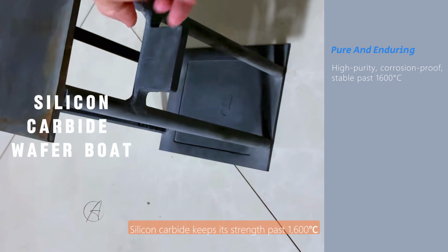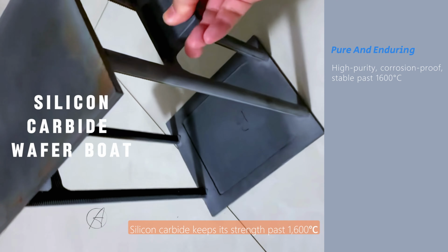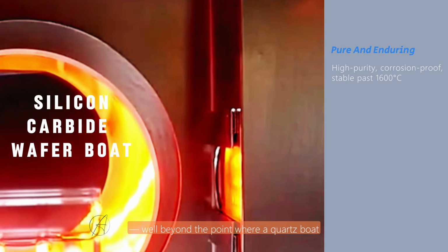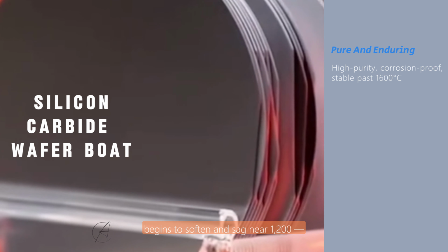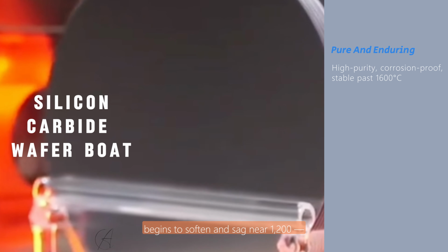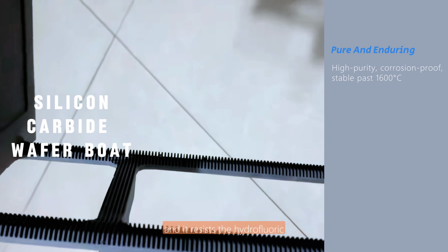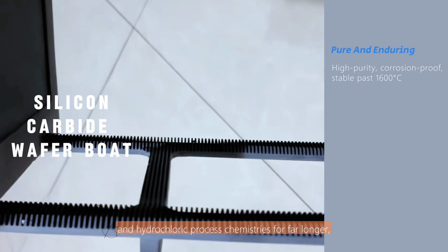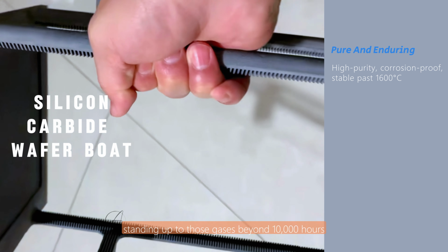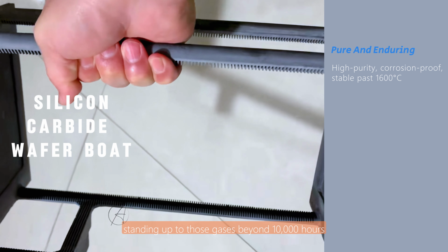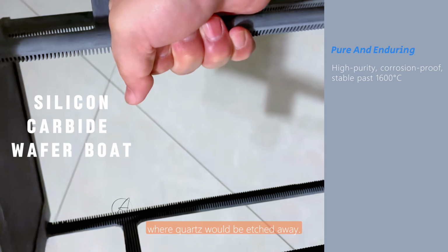Silicon carbide keeps its strength past 1600 degrees, well beyond the point where a quartz boat begins to soften and sag near 1200. And it resists the hydrofluoric and hydrochloric process chemistries for far longer, standing up to those gases beyond 10,000 hours where quartz would be etched away.